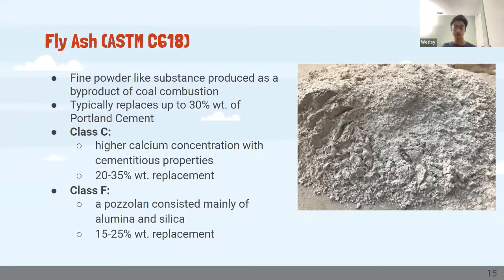And it's essentially an international organization that makes a lot of standards for industry materials, and specifically for fly ash, it's ASTM C618. And so essentially what fly ash is that it's a fine powder-like substance produced as a byproduct of coal combustion. And these can typically replace Portland cement, which is the most common type of cement used around the world, by up to 30 weight%.